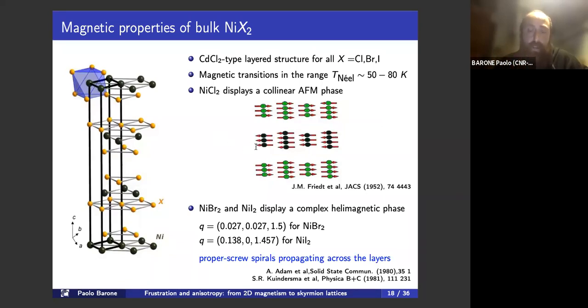But what is most interesting is that nickel dichloride is the only one with a collinear magnetic phase in the bulk system, while the bromine and iodine counterparts of this subclass of materials were both reported to display a very complex magnetic phase. Here I report the experimentally found propagation vectors for the spiral phases, and you see that basically they have a very strong out-of-plane component, but also an important in-plane component. So these spirals are going across the layers, and from the neutron scattering measurements, the experimentalists deduced that they should be proper-screw spirals.